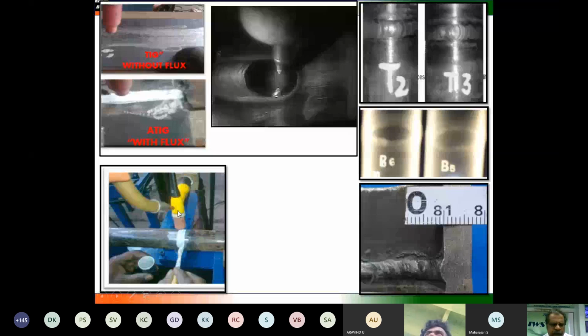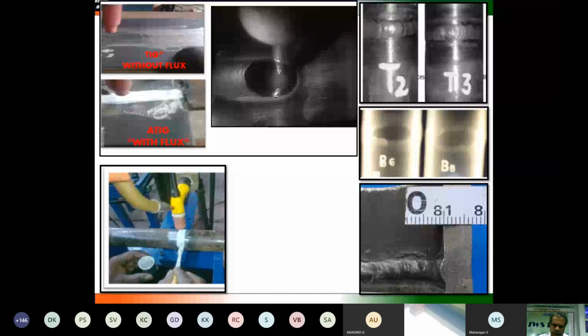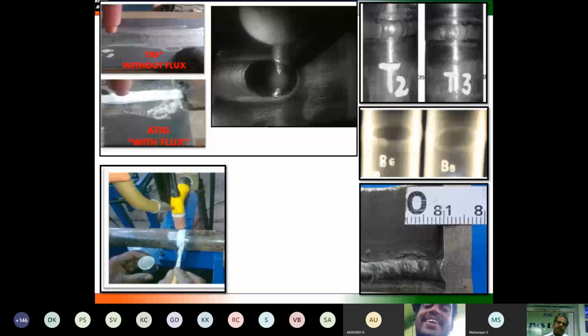We tried to use it for manual TIG welding, which was a little bit difficult for us because always the arc should be focused on the material, which is difficult for the welder to maintain. But in any semi-automatic or orbital welding process, this has been applied successfully, and we are very successful in making RT quality welds meeting the ASME requirements, American Society of Mechanical Engineers requirements. So this is another development that happened in the process.